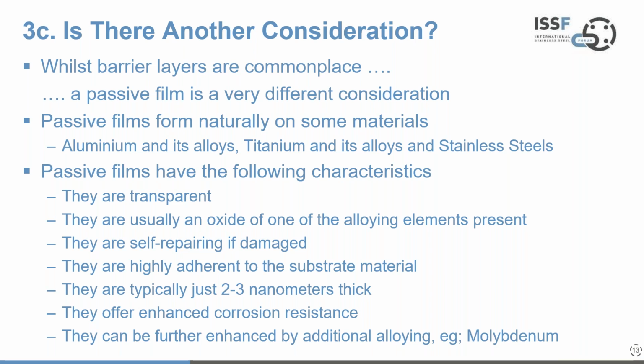And you can always further enhance these passive films as well, where you've got more aggressive environments. So in the case of stainless steels, molybdenum is a great element that can be added to give increased resistance against something known as pitting corrosion, which I'll talk about a little later.